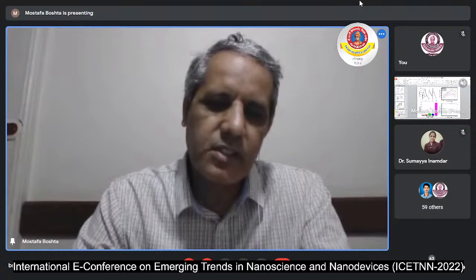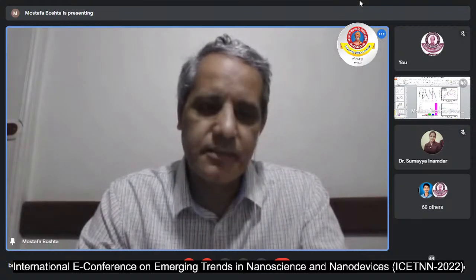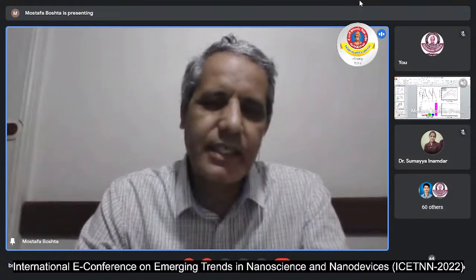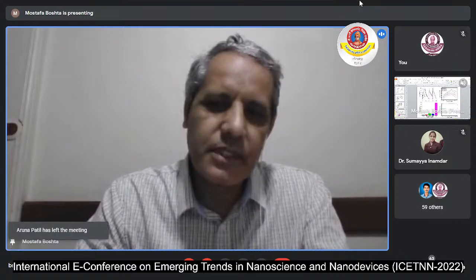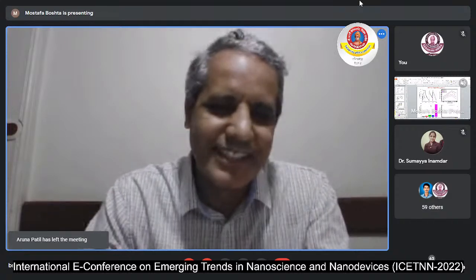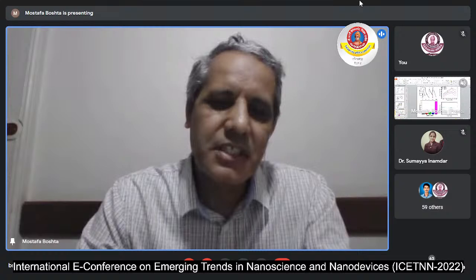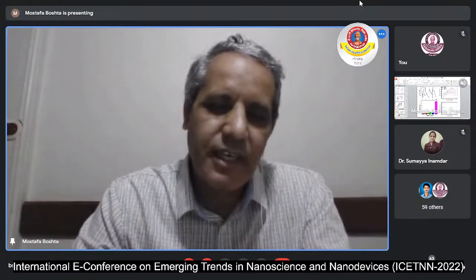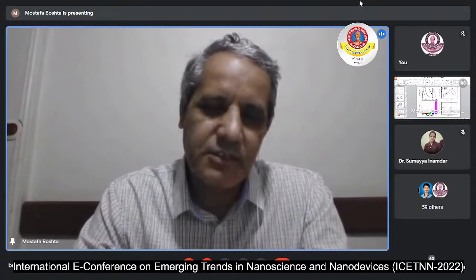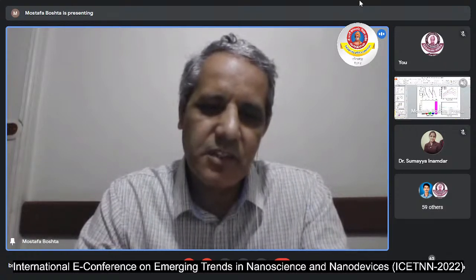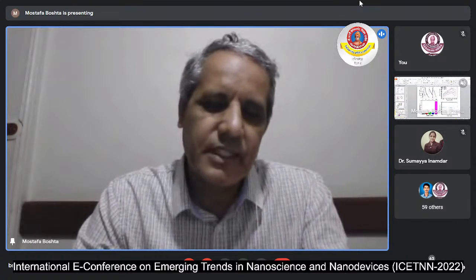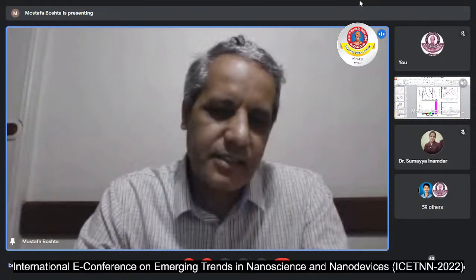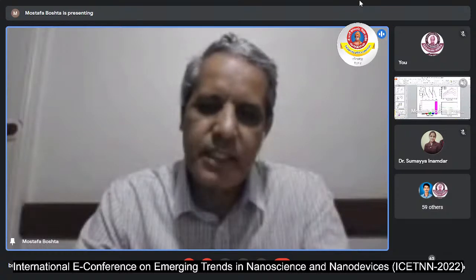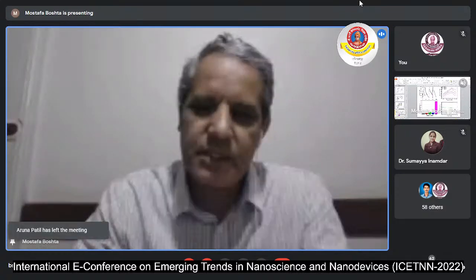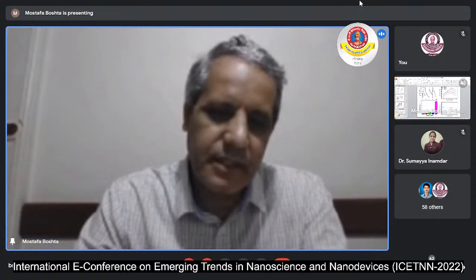And we also check this nickel oxide layer deposited by spray pyrolysis with different gases, and we can see, sorry, I made a mistake. This material is not measured in Sweden. This is measured in India with Professor Patil in Kolhapur, at Shivaji University, and they measured the sensitivity of our sample. They also tested the sensitivity of this sample for a lot of gases, but we found that nitrogen oxide is the highest one for this layer of the material. They also checked the stability of the material, and we found that for 20 or more than 20 days the material is still stable and gives the same sensitivity and the same performance.